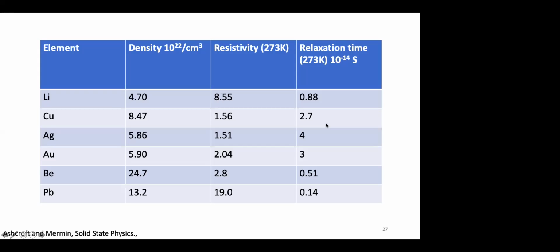So what it means is that the electron can only go in a straight line between atoms, which is experimentally not shown to be true. They have shown that in pure materials, electrons can travel several microns, which means it can go past millions of atoms. It just passes through millions of atoms as if it did not see the ions itself. So these are all experimental proofs which say that Drude's model is not completely true. It does not satisfy all experimental observations. There are still issues.